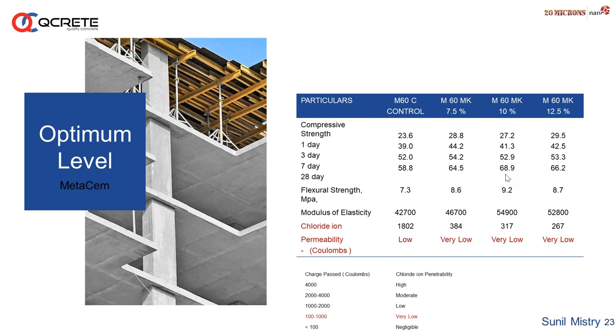So we need not add more quantity unless it's required for a special purpose, like marine concrete or where the environment is much more aggressive, where we can compromise a little bit of strength, but durability is more important, or chemical attack has to be taken care of. Next, you can see the flexural strength is also increasing as the replacement increases, and decreases a little bit at the 12.5% replacement of the cement.